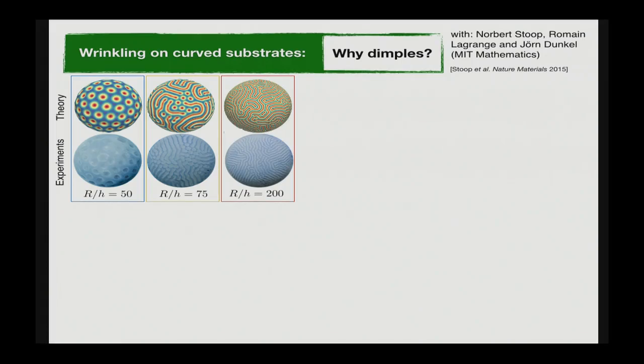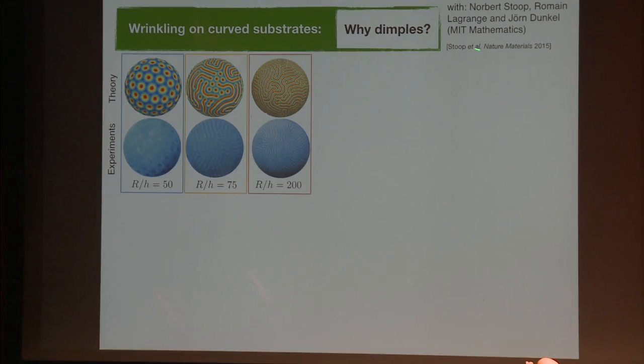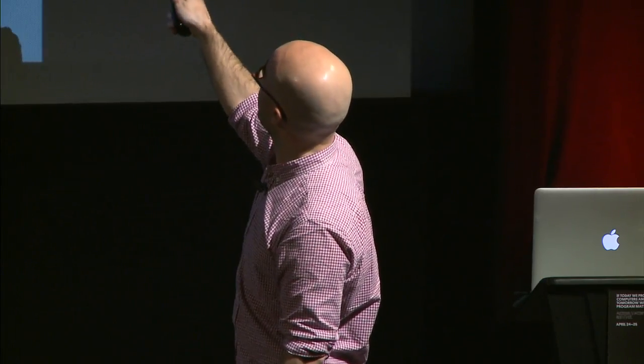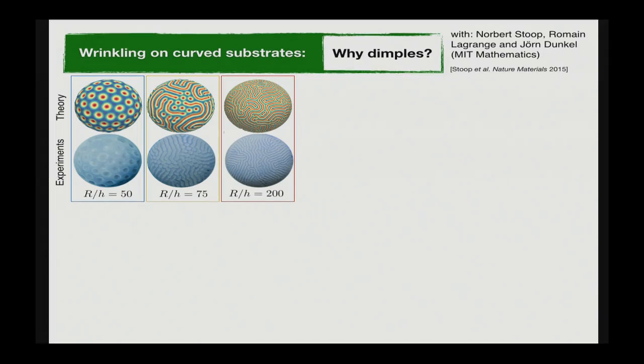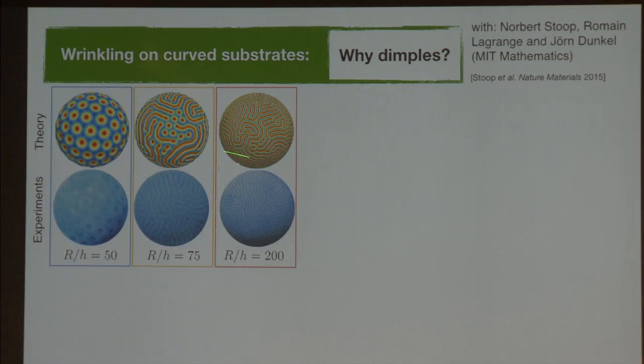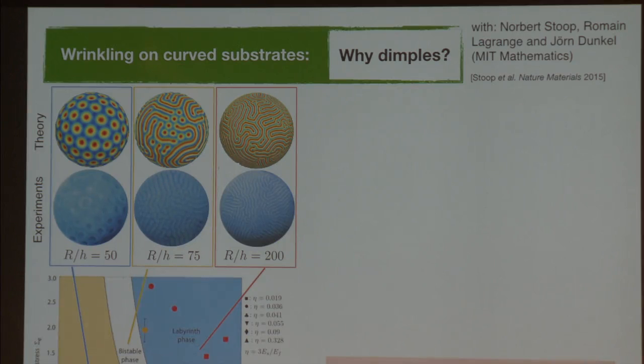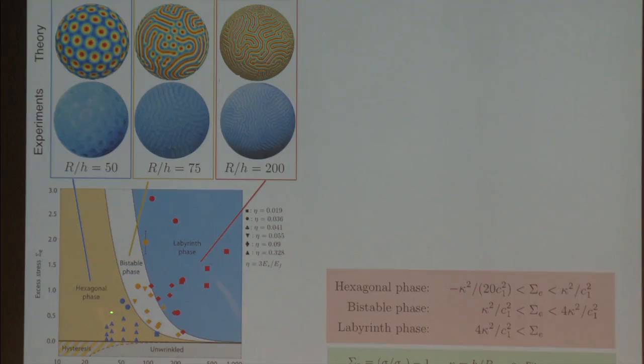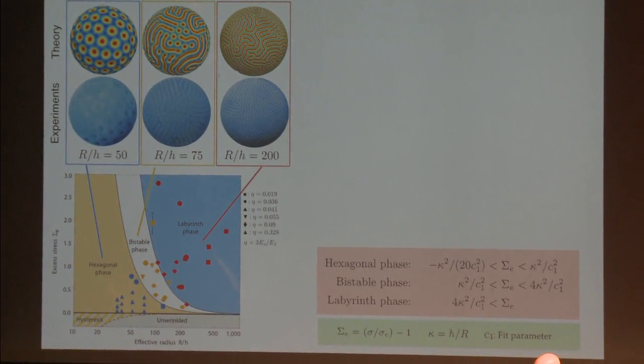Now, this is probably the slide with the largest number of equations in the conference, so I apologize. But first, let me give you the results. So the question is, why do we modify the result that we obtained for the flat case. And this is work done in collaboration with Jörn Dunkel from the math department at MIT, again, with two wonderful postdocs. They really developed this model. These are our experiments, so we can get either dimples or an intermediate mixed phase or labyrinths, and they can predict that exactly. This is the same phase diagram that I showed you before. So now we can put theory on top of experiments, and theory lines very nicely separate the various phases. So we have predictive value here.